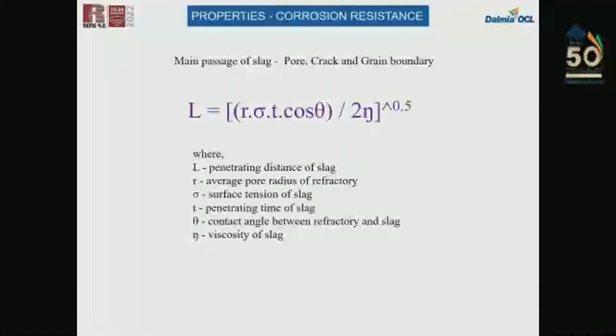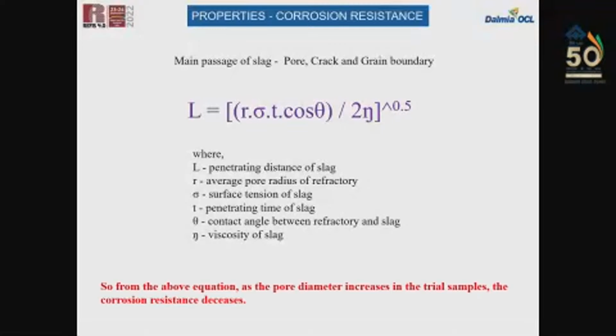I am talking about the pore size distribution, and that is because this is an equation on which the penetration of slag inside the refractory depends. L is the penetrating distance and R is the average pore size. So as R increases, the penetration will also increase. So we need to keep this pore size minimum to stop this penetration.